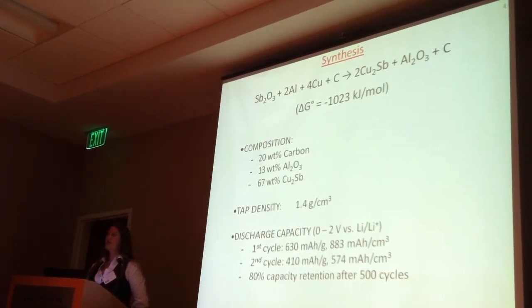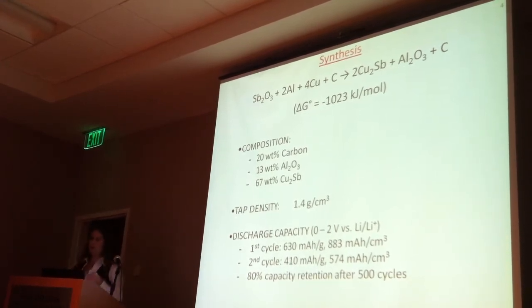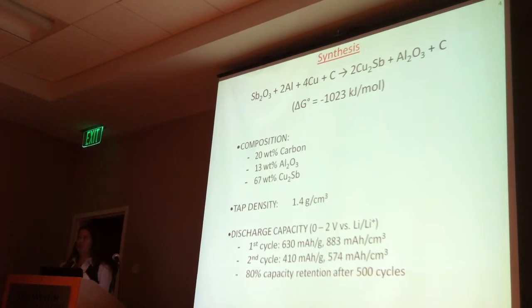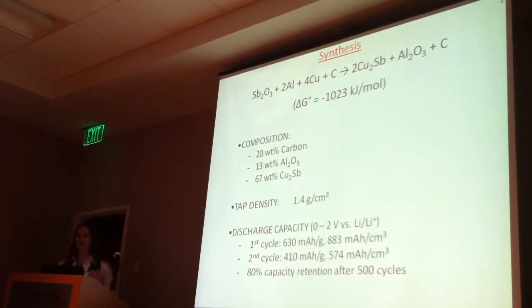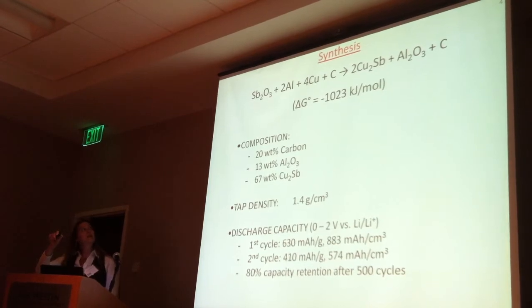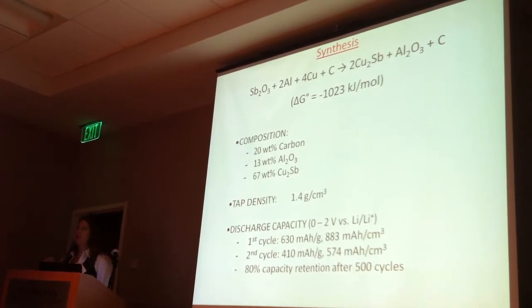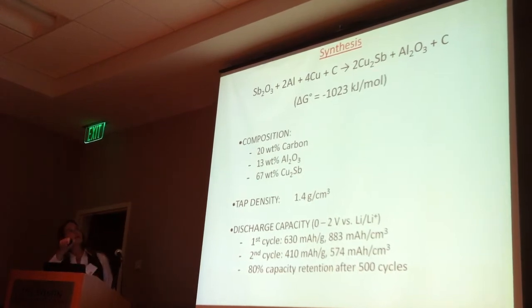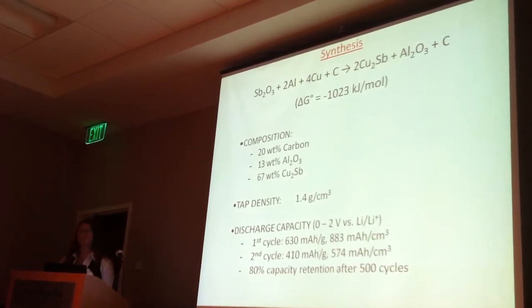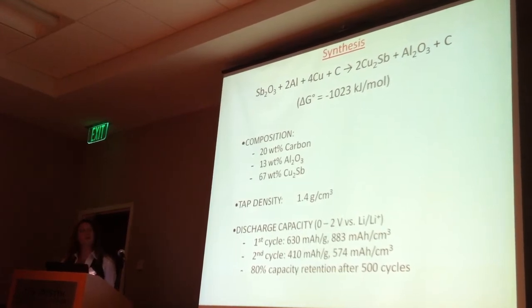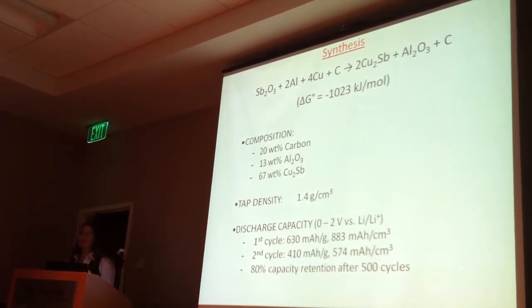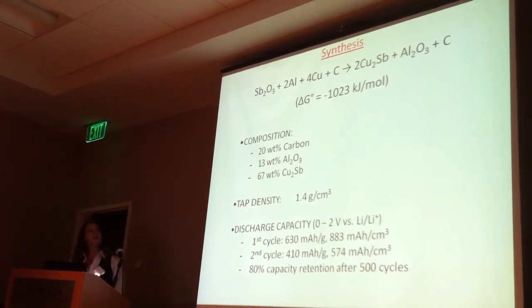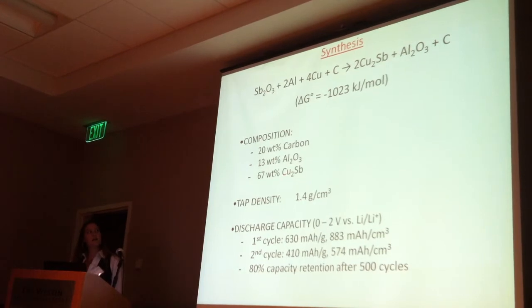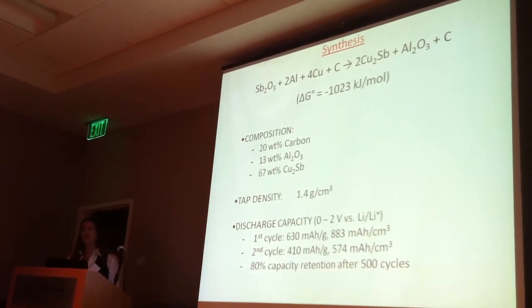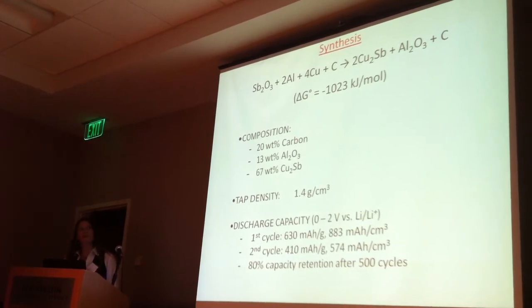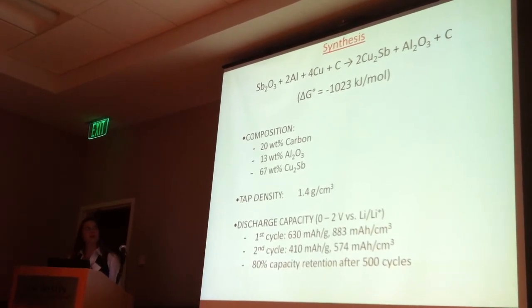So we chose a different strategy. Instead of the typical copper metal, antimony metal ball mill, we decided to use a mechanochemical reduction where you take antimony oxide, aluminum metal, copper metal, and carbon, and you ball mill it. And so the reaction that makes this alloy happens inside the ball mill. This reaction has a negative Gibbs free energy, so it proceeds spontaneously, and what you end up with is a material where the ratio between the aluminum oxide and the Cu2Sb is fixed. It's a stoichiometric relationship. What you can vary is the weight percent of carbon. We just chose 20 weight percent.